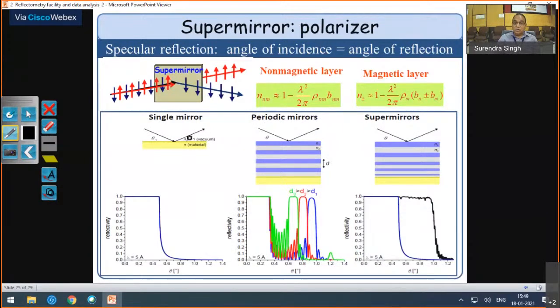You can see if you have a single layer, the reflectivity looks like this. When we have a perfect multi-layer, we get a Bragg peak.